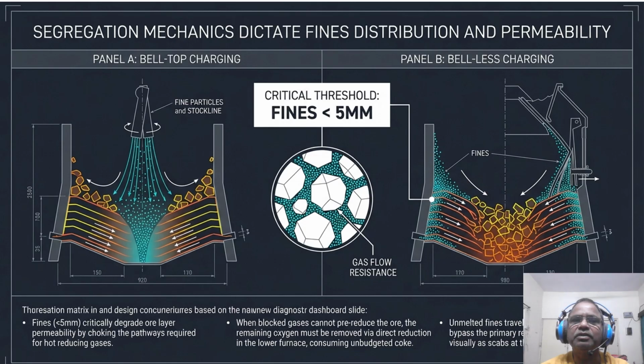The critical threshold here is 5 mm. Anything smaller than 5 mm is a fine that chokes the ore layer pathway required for hot reducing gases. Look at the magnified center graphic. These fines create massive gas flow resistance.